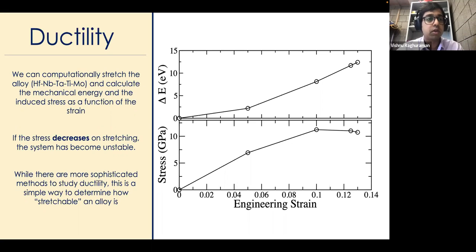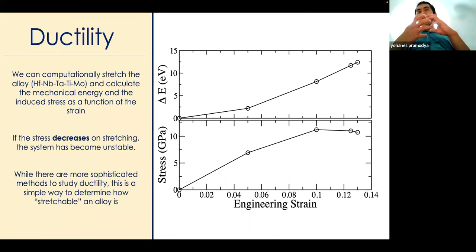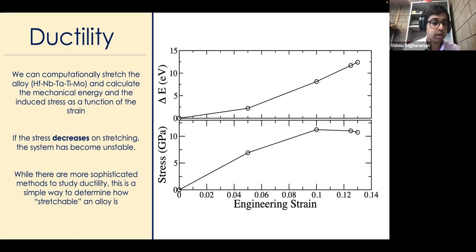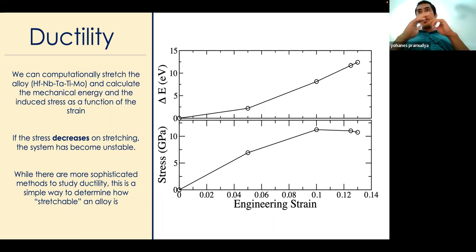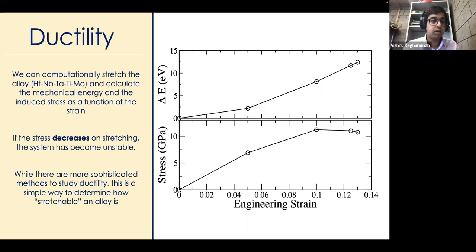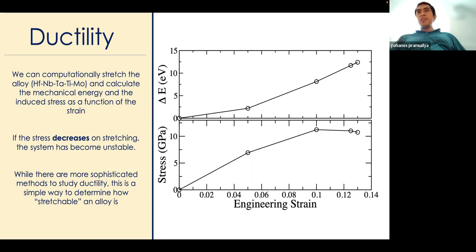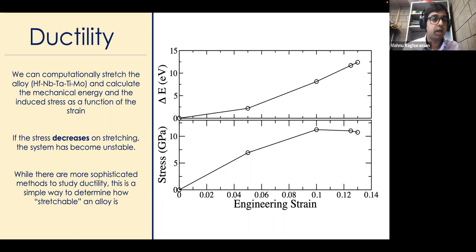Yeah, so you create different structures and then you treat them separately. Okay, so you keep the symmetry for the temperature, like doing a vibrational calculation. So that's an easier way. You could also, as mentioned, create a really large supercell, and then if you do molecular dynamics at different temperatures, you will see the change in crystal structure. Oh, so you let them change by themselves, so you don't constrain the volume. Yeah, you can do both. If you know that these are the two phases that exist, you can create separate structures for these two and then compare the energy. Then you can also create a really large cell and do MD at different temperatures. If you look at the results of that MD, you'll see that below a certain temperature it'll look a certain way, and above it, it'll look a different way. So you will be able to see that phase transition in MD, even though that's very expensive computationally to do. Okay.